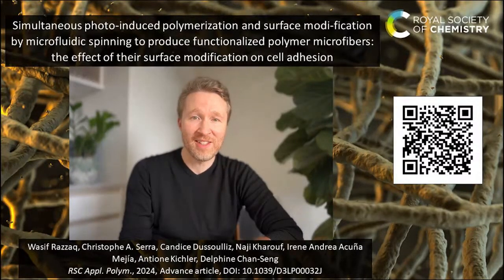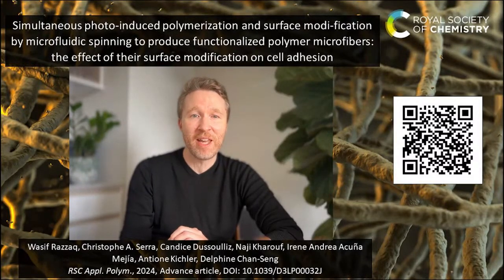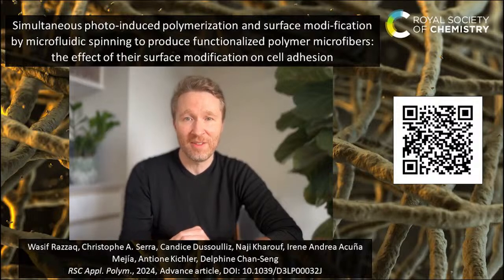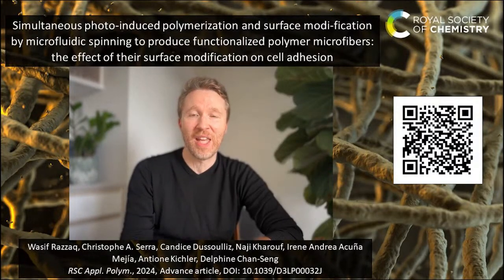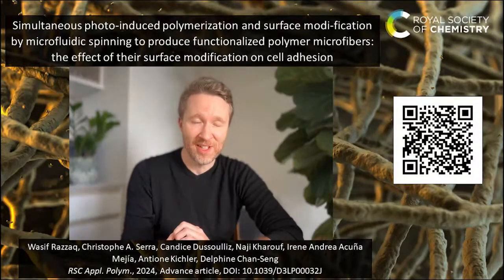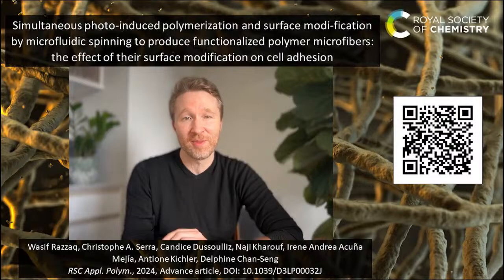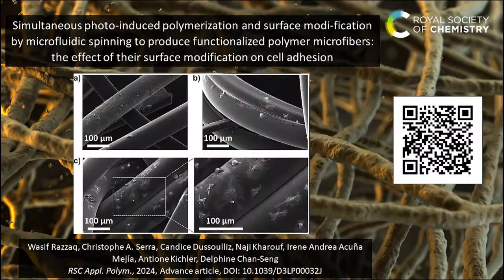Looking at the results of the resulting polymer fibers, they were able to show that many different surface functionalities were able to be introduced, and in particular the thiol groups had an impact on the wetting properties and surface roughness of these fibers. And this was beneficial in particular for cell binding. They incubated these fibers with RAW macrophages and human colon cancer cell lines and could see an increased cell adhesion to the surface of these fibers.